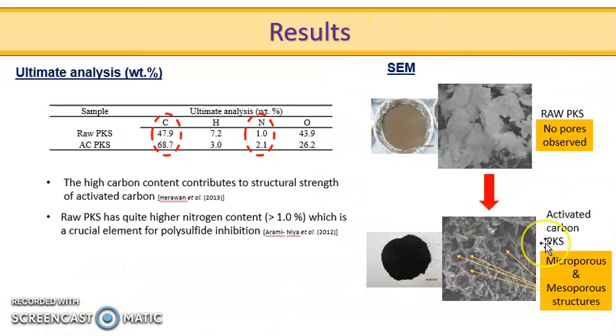And as we can see from the SEM result, the raw PKS has no pores observed. After the PKS undergoes several treatments such as a temperature of 500 degrees and impregnation ratio of 1, using potassium hydroxide, we can see that micropore and mesopore structures are observed in this figure. This is a very crucial factor to trap the polysulfide inside this porosity, or the structural porosity here.